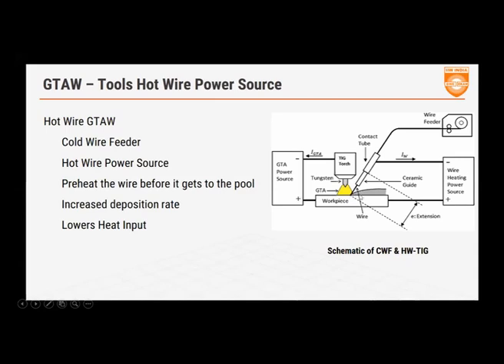Now, if you wanted to increase your productivity, you could preheat this wire before it enters the pool. If you preheat the wire, the energy needed to melt it goes down, thereby allowing quicker deposit rates. The hot wire power source could be connected straight at this point here and to the job. The longer the extension, the more heating of the wire can happen. It creates a resistance through which the current flows. This allows the wire to melt at a lower current or lower heat input. Therefore, the average heat input on the job goes down and your deposit rate increases.